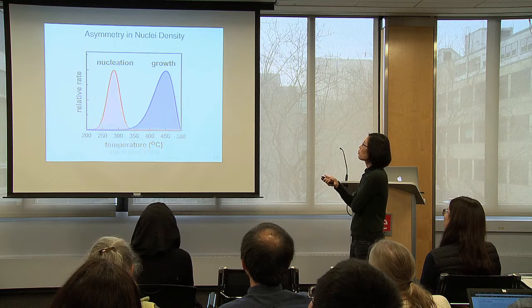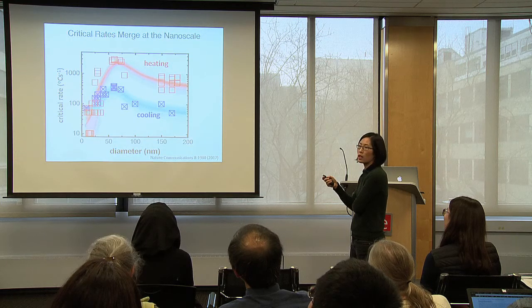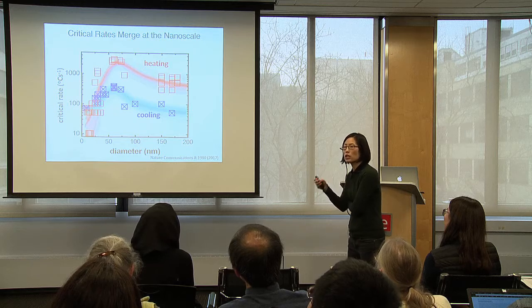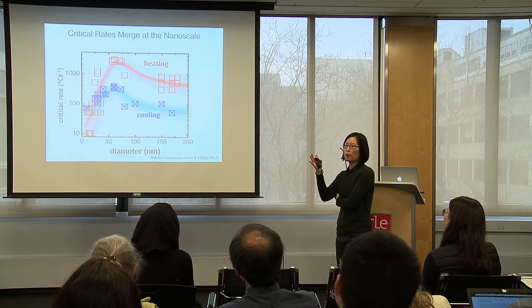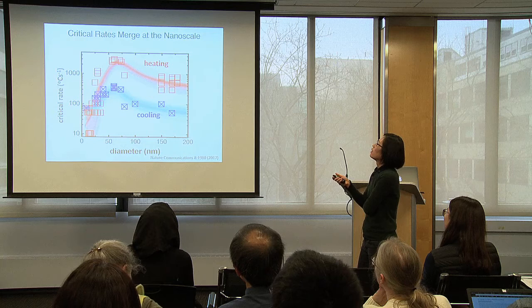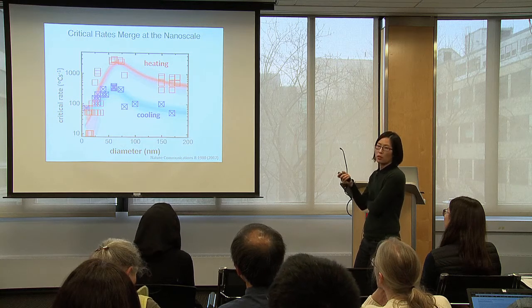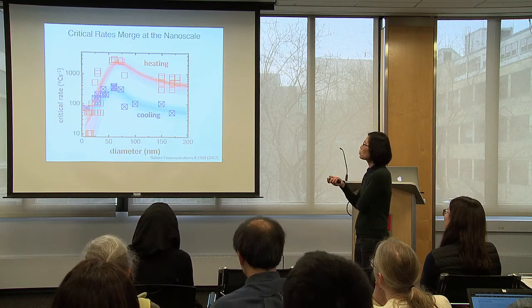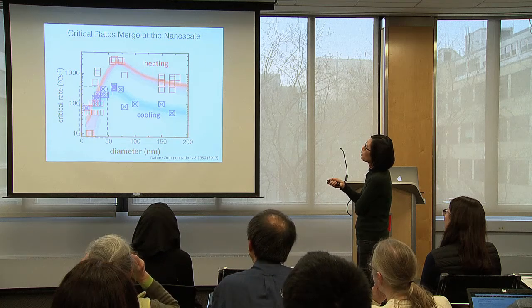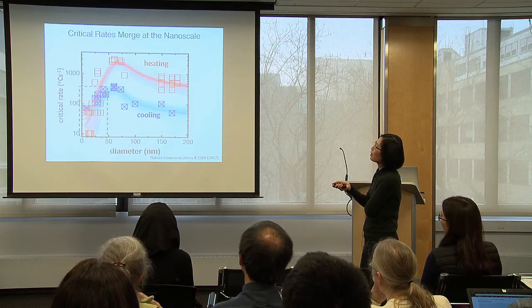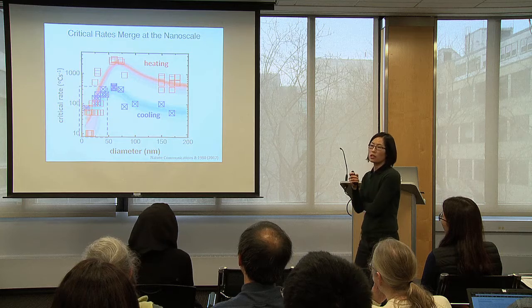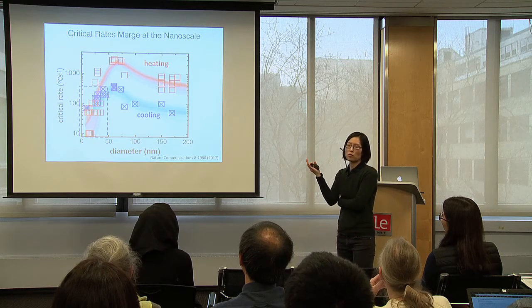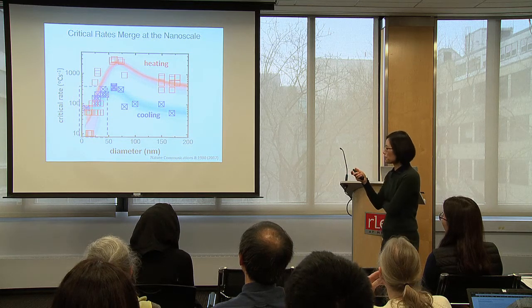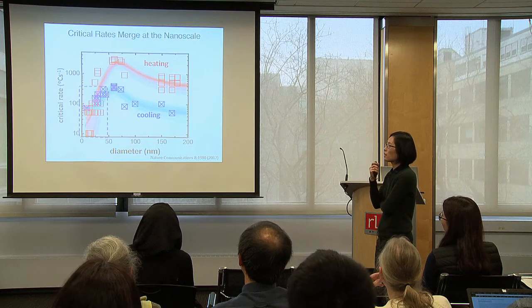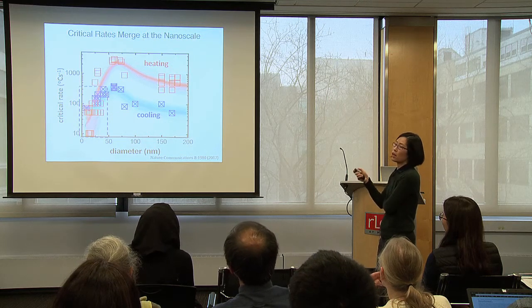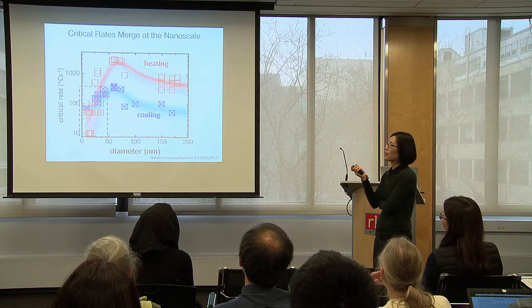Okay? So that's a way to explain critical heating rate is faster, meaning it's easier to crystallize coming from glass up. So the rate has to be faster. So that's confirming what's already been observed. What was new to us was the fact that below about 35 nanometers in diameter, the critical heating and cooling rates merged. Okay, so that was never observed. I mean, people never looked at these small sizes. So we see that the asymmetry at larger scale disappears.